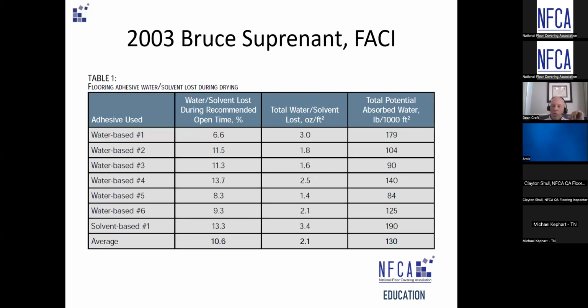Remember, the limit all the way through this time period for concrete was 3 pounds of moisture. So they actually equated this to pounds of moisture per 1,000 square feet, and the average was 130 pounds. The limit for concrete was 3 pounds. So the water itself, on average, or the available free water or solvent in these adhesives, were contributing upwards of 130 pounds per 1,000 square feet.